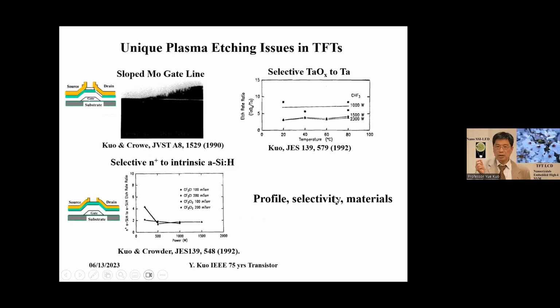This one shows an example for display TFT. Because of the structure, the gate dielectric is deposited on the gate, and subsequently we deposit different layers, so step coverage is very important. To provide conformal step coverage, usually the gate metal has to be sloped, which is very different from the IC.